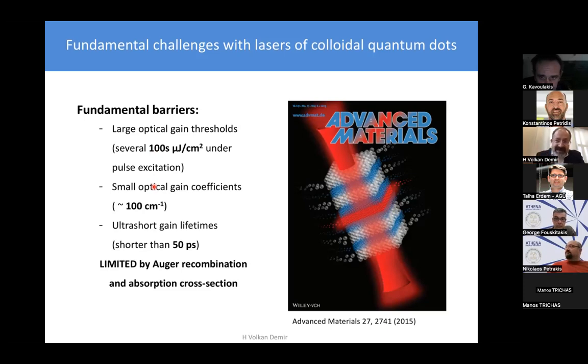And quantum mechanically, the limitation really comes from Auger recombination. No matter how much we try to suppress this, eventually Auger kicks in, at one point, as we keep increasing the pump. Also, because these are quasi-zero dimensional and we need to keep certain size, absorption cross-section is limited. So with these fundamental limits in mind, one has to go to different strategies.